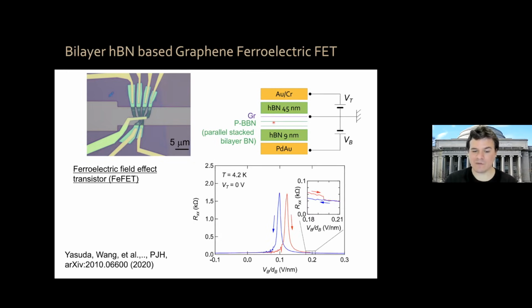And indeed, if you measure the resistance of graphene versus electric field, we see that it has this large resistance peak. Remember, in conductance it's V-shaped, in resistance it's a peak near charge neutrality. So we have the resistance goes up and down, and then if we sweep backwards, it goes up and down at a different place, okay? Which means this material exhibits hysteretic resistance, okay?